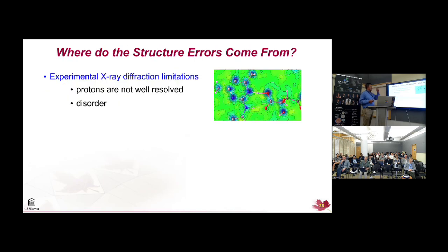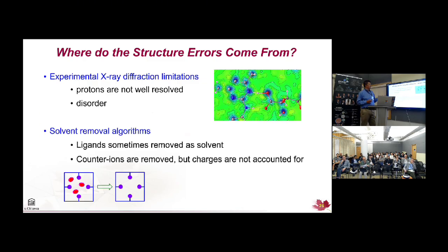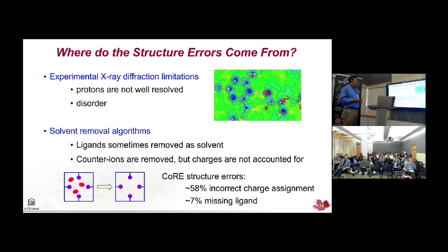Okay, so where do the errors come from? Some of them come from the limits of the XRD experiments, but those are well known. Protons sometimes aren't well resolved, there's disorder, but it turns out the majority of the errors from our analysis come from the solvent removal algorithms, the pre-processing algorithms people were using. For example, in the CoRE structures, a lot of the errors come from missing protons, but 58% also come from wrong charge assignment. So they removed the counter ions and didn't account for it. And then, of course, when people were building hypothetical MOFs, they used building blocks from this database. So that's why some of them have 70% errors.